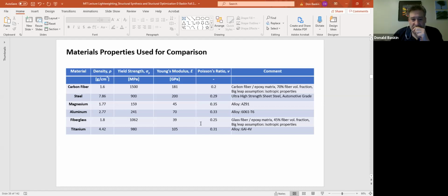The final material on this chart is titanium. Titanium has a density roughly half that of steel, 4.42, actually less than half. I'm sorry, more than half, about 60%. So 4.42 grams per centimeter cubed. The yield strength is 780 megapascals, or sorry, 980 megapascals, so about a gigapascal. The Young's modulus is 105, a little tiny bit more than half that of steel.